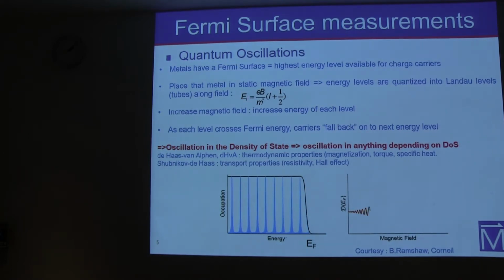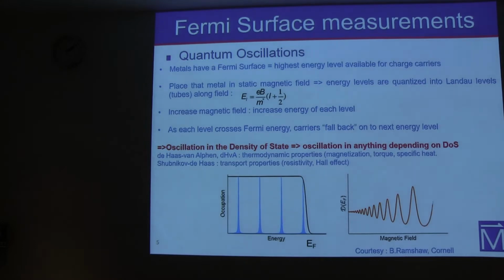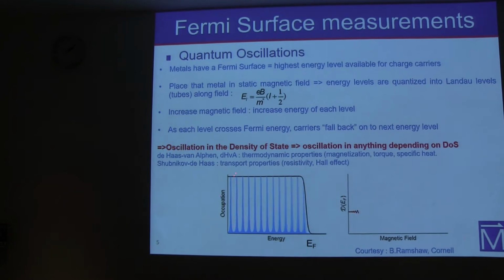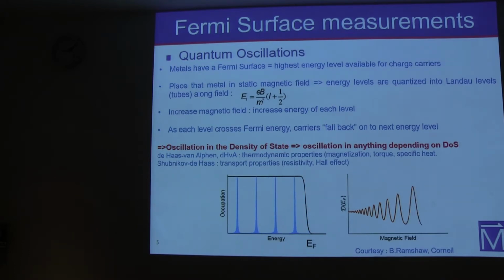So what happens when you increase the field so much that the energy becomes greater than the Fermi energy? All the carriers that are located on that energy level fall back onto the next available authorized energy level. And this is what is shown here in this animation. Here we show the occupation as a function of the energies. And when the field is increased, the energy also increases, and the charge carriers fall back onto the next available energy level.